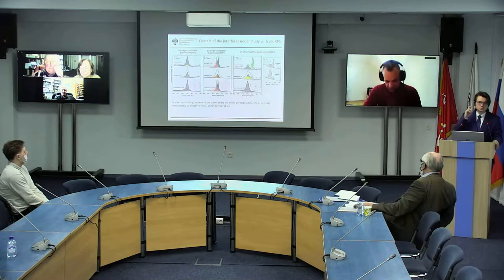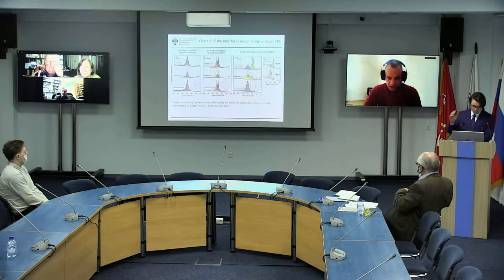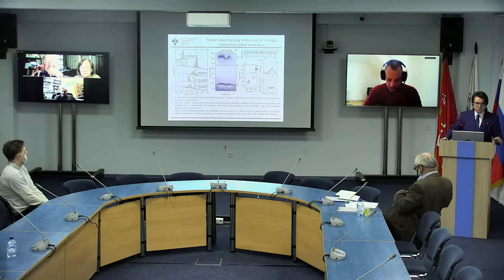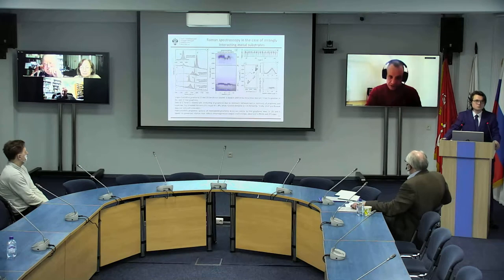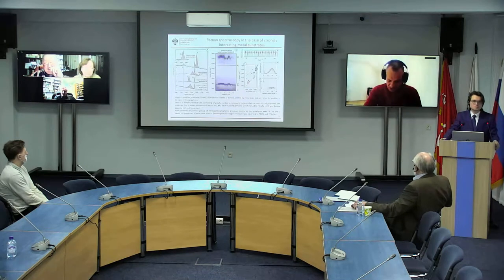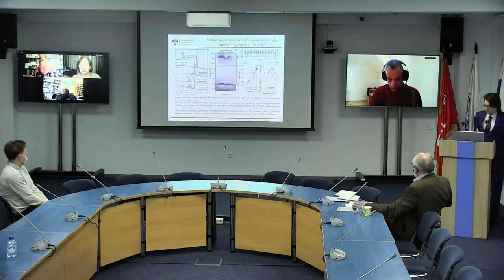And this model relies on the band structure, and essentially it claims that this double resonant Raman process is not possible in the case of this heavily, strongly interacting graphene. But when he has polycrystalline graphene, he actually found both the 2D band and the D-band. And essentially, all this Raman work is nicely in line with the works by LEED and by XPS that he has also shown.